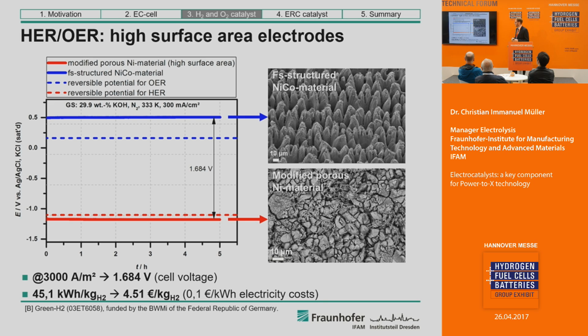If you use these electrodes in an electrolyzer and you calculate the cell voltage, you see that you get a cell voltage of 1.6 volts at a current density of 3000 amps per square meter. This means that you need around 45 kilowatt hours per produced kilogram of hydrogen. And assuming electricity cost of around 0.1 euros per kilowatt hour, you can produce hydrogen for less than 5 euros per kilogram.